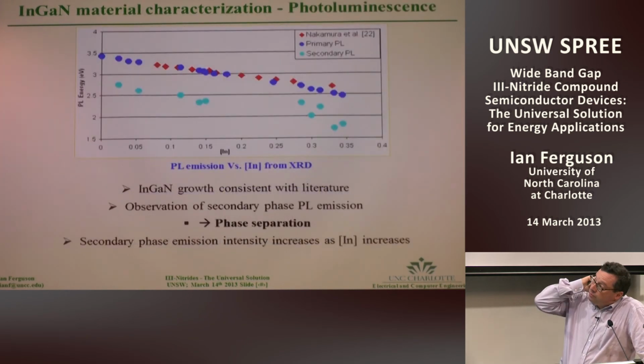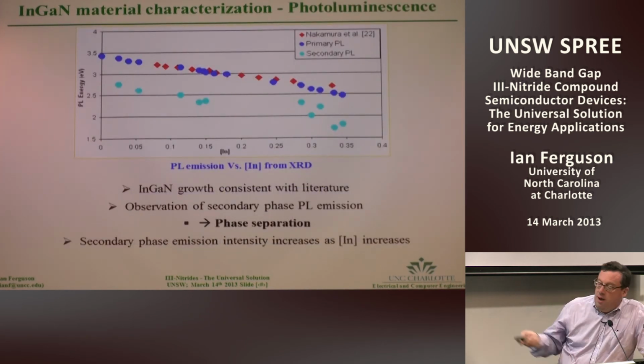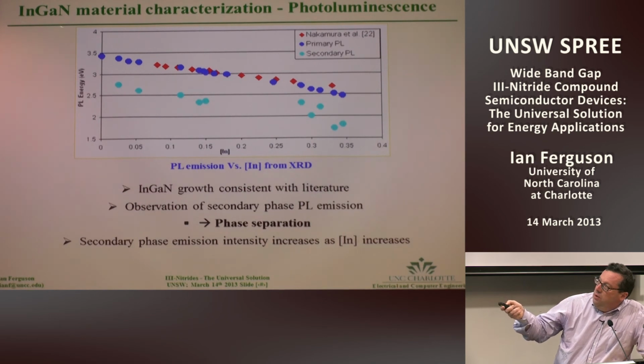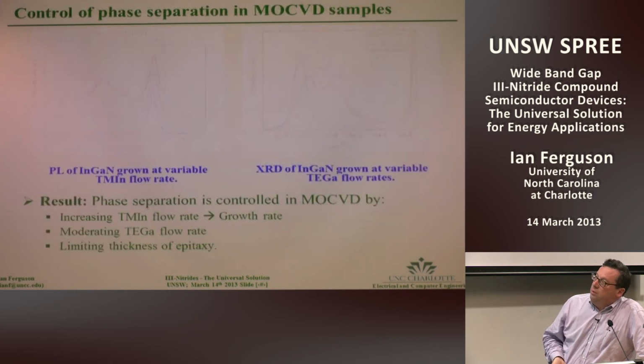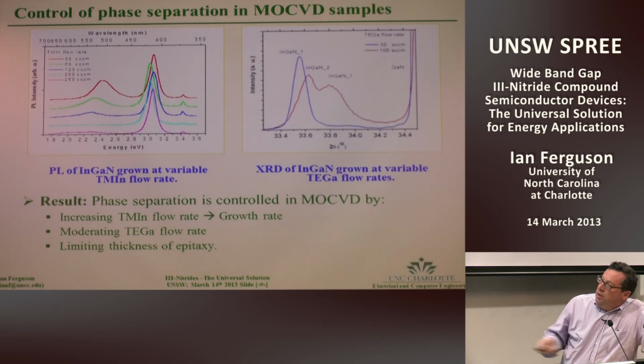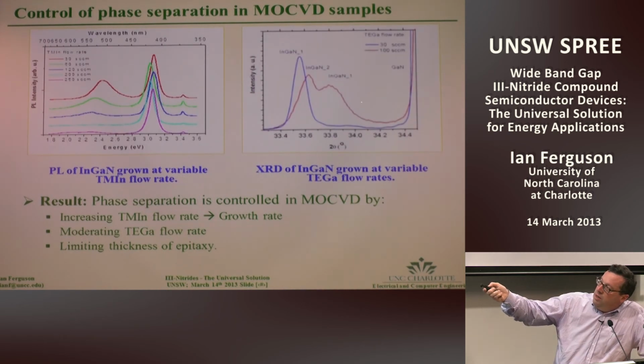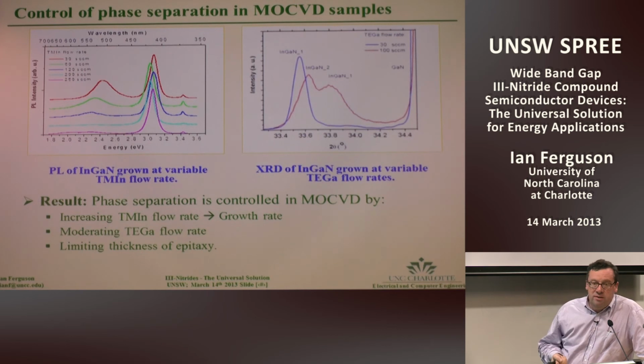This is also shown in PL measurements over the region that we were interested in, and certainly you can see if we weren't controlling the phase separation, you could see second order or secondary PL peaks. So the trick here was, how do you take material that would separate out and make it single phase? And a lot of this, again, I don't have time to talk about, was how you control the kinetics of the growth system to make the material uniform.